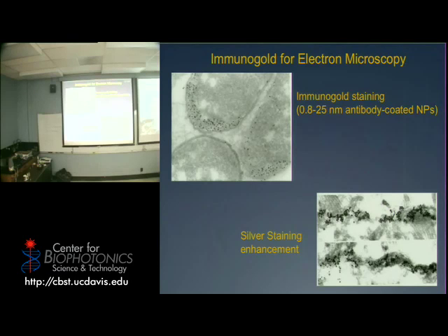And you can use these for doing what is called immunogold staining. Say you want to see if a cell has a particular type of receptor, so you buy or make a gold nanoparticle that has the complementary to that particular receptor, whatever the complementary is. You stain them just by simply incubating them. You wash them out, and you use a technique like typically scanning electron microscopy or transmission electron microscopy. And because of the density of the material, they appear like little dots, like so.